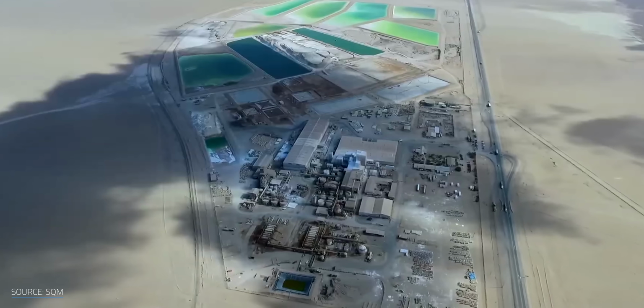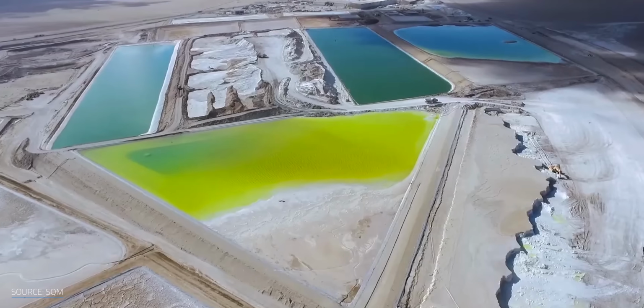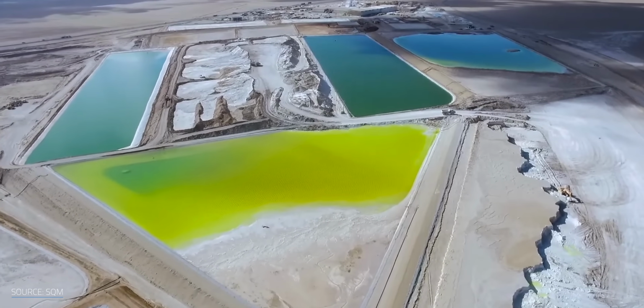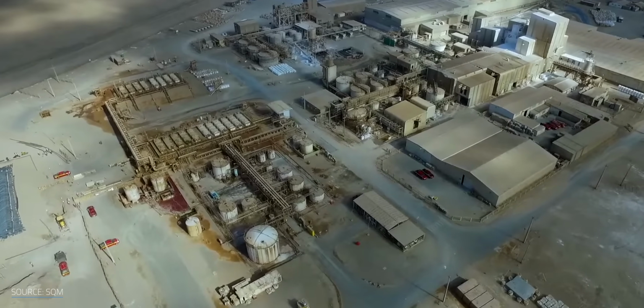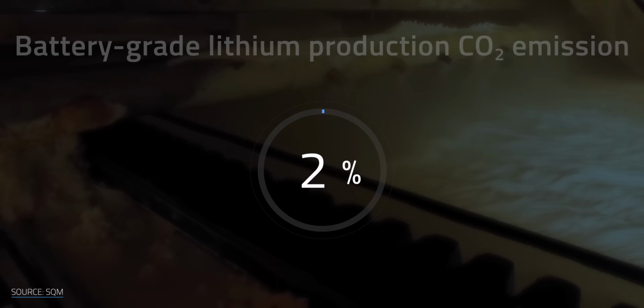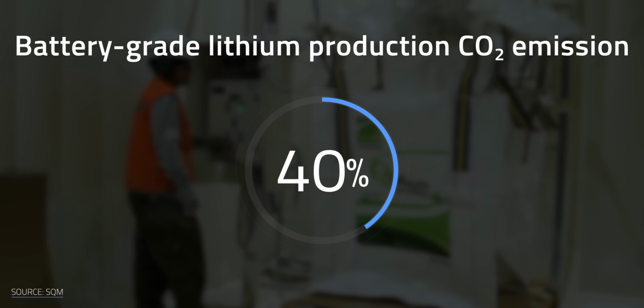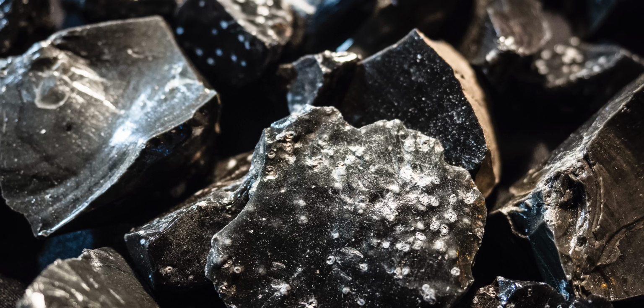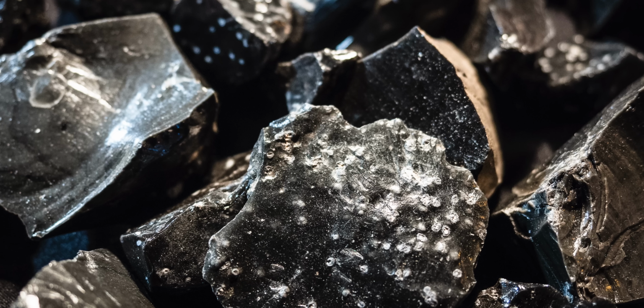Refining it to battery-grade lithium carbonate contaminates the few drops of leftover water with toxic metals such as antimony and arsenic, which means even less usable water for the indigenous people. On top of that, the manufacture of battery-grade lithium accounts for 2% of the device's carbon emissions. Lithium is not the only high-carbon ingredient of traditional batteries. As of today, the anode of lithium-ion batteries contains graphite, which is a carbon-based and carbon-intensive material.